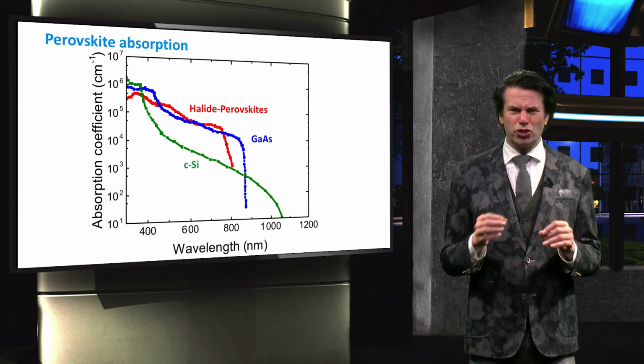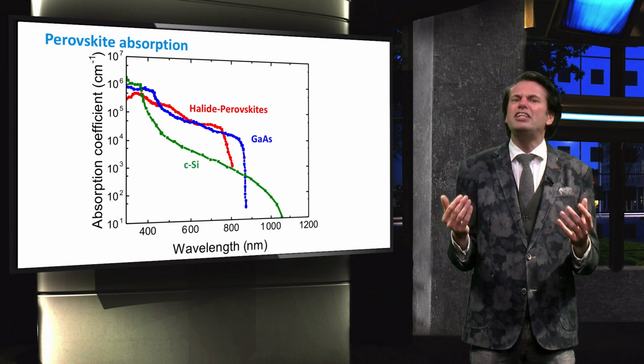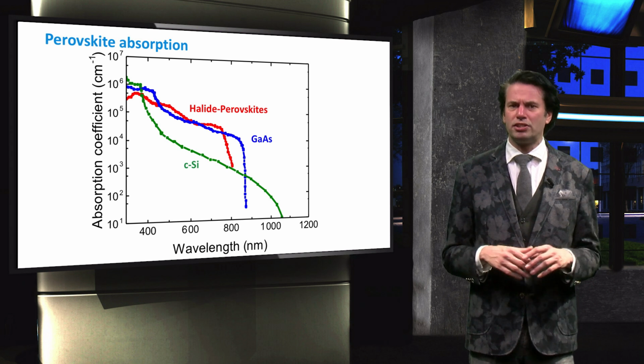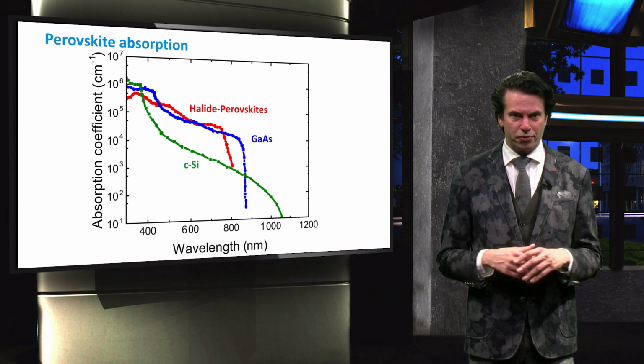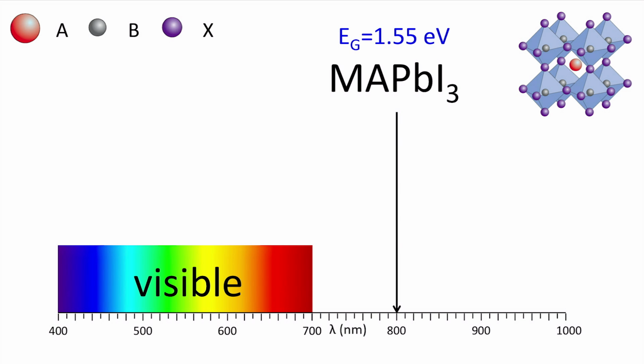The perovskite material does not have a field-dependent exciton dissociation. Also, due to its defect tolerance, the low trap densities in the bulk result in a long intrinsic diffusion length and relatively long carrier recombination lifetimes. The band gap can be tuned by the composition and can range from 1.3 up to 2.3 electron volts. The standard methylammonium lead iodide perovskite has a band gap of 1.55 electron volts, or 800 nanometers expressed in wavelength. The halogen anion X, or iodine, can for instance be replaced by bromine.